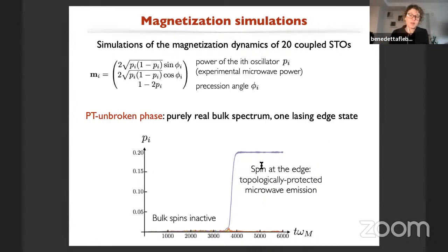What happens in the nonlinear picture? Well, what happens is pretty surprising. We start pumping spin currents in all these sites, but the only site that starts precessing is the spin at the edge. And this is a topologically protected microwave emission. We tried to run this simulation for a long time, and in many realizations, the bulk keeps staying inactive. So this is definitely an effect that you would never have expected from a simple classical perspective.